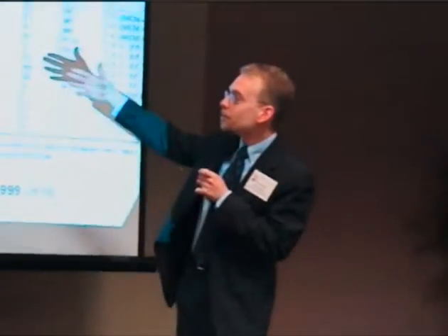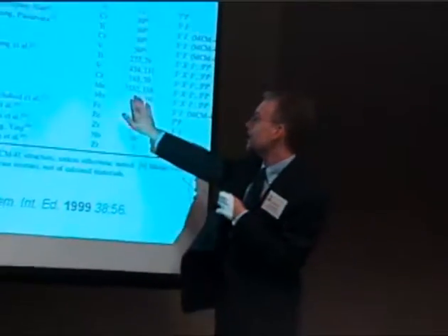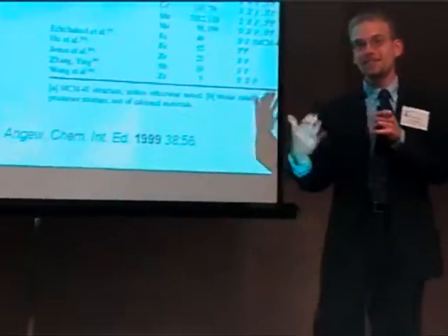The main limitations, though, are in understanding how to do that and how to introduce the level of loading that you want in the materials. This table also includes a silica to dopant ratio, and some of these numbers are fairly small, like six silicons per aluminum, but some are very large, like on the order of 3,000 silicon per manganese, so it's a very low level of loading. And I think that's the challenge people face: they don't really know how to introduce the transition metals exactly how they want to get good catalytic performance.